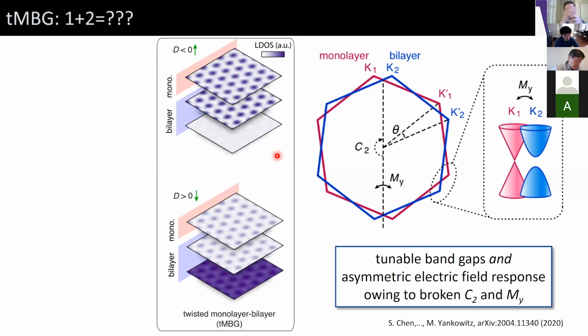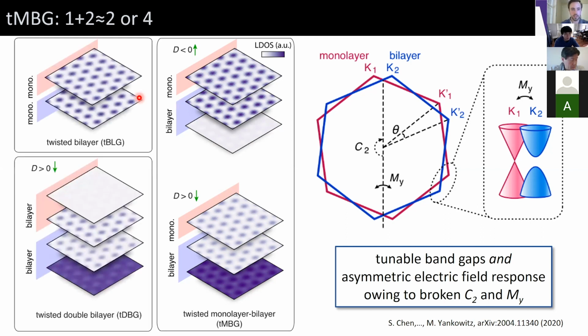and arranges itself on this triangular lattice of AB stack sites, where basically the lattices exactly sit on top of one another. And then this outer layer of the bilayer graphene has very, very low local density of states. So it's basically a small amount of charge in that layer. Whereas in contrast, if we flip the electric field and have it point towards the bilayer graphene, the arrangement of the local density of states is still similar. It's still peaked on these AB sites. But now we've pushed a lot of the charge towards this outer layer of this bilayer graphene. So these two systems look very different depending on the sign of the electric field. And in fact, what I want to convince you of is that there's kind of a simple analogy we can make to either twisted bilayer graphene or twisted double bilayer graphene, depending on the sign of the electric field.